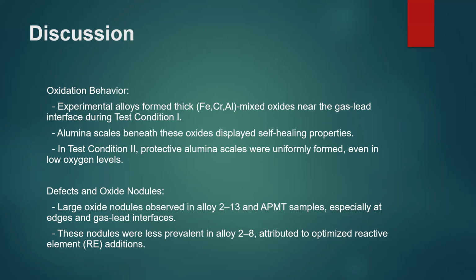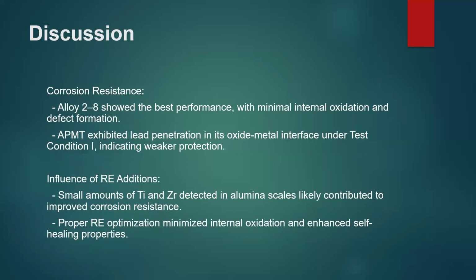This nodule was less present in alloy 2-8, attributed to optimized reactive element addition. For corrosion resistance, alloy 2-8 showed the best performance with minimal internal oxidation and defect formation.